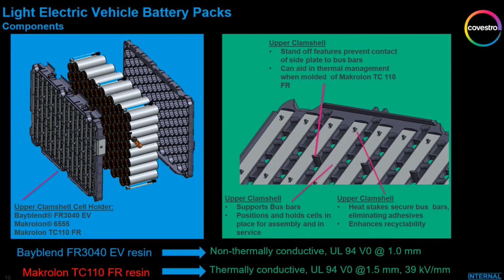So if we look inside the pack, we had some components that we designed specifically out of our materials. First and foremost, the clamshells. The clamshells hold the cylindrical cells in this case. And we looked at several different material grades, primarily Bayblend FR3040 EV. I mentioned that earlier. That is a non-thermally conductive, flame retardant material, flame retardant PC/ABS. And as I mentioned, it is transparent at UV wavelengths to allow curing of UV adhesives through it. So really good choice for these types of applications. It's high flow and it will fill the thin walls very nicely.